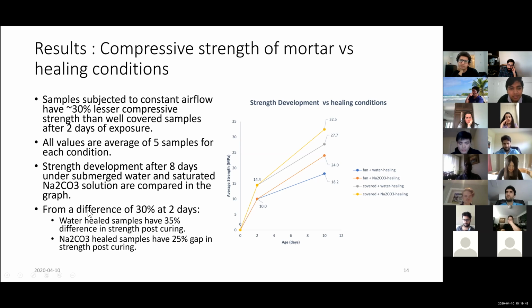To calculate some percentages, I did this calculation. So there was a difference of 30% at 2 days. In this case, there was a difference of 35% in water healed samples. So basically, this one and this one, there is now a 35% difference post curing, and in sodium carbonate healed samples it's a difference of 25%. So we can say that sodium carbonate has helped reduce this loss of strength in the early age, and it's definitely performing better than water curing.